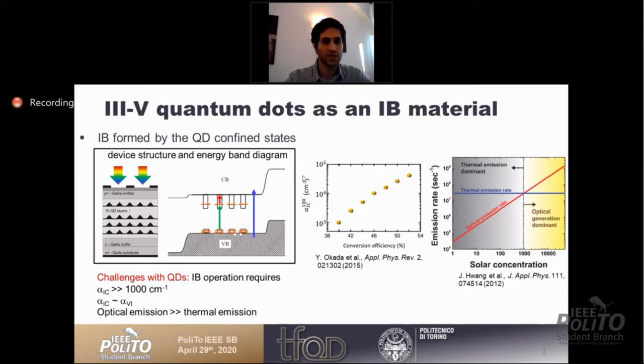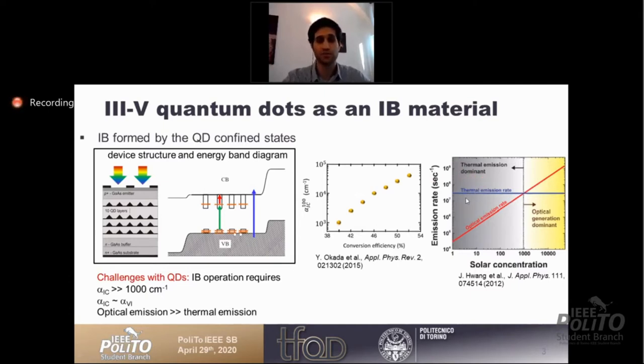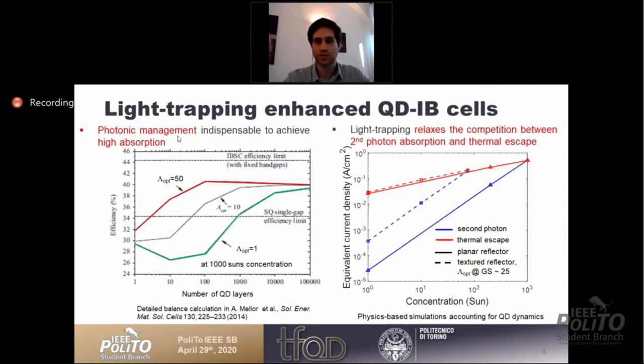We also have another issue with intermediate band solar cells fabricated in recent years: the problem of thermal escape, which competes with optical emission. At very high solar concentration, optical emission dominates. But if solar concentration is not high enough, carriers escape thermally. This competition is one of the main topics tackled in this work, and thermal emission also competes with second photon absorption.